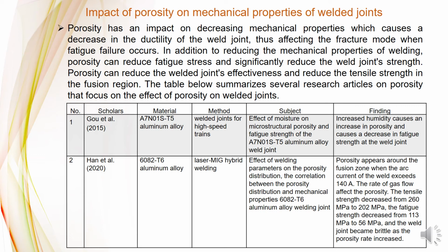Number 2, Han et al. Material: 6082-T6 aluminum alloy. Method: laser-MIG hybrid welding. Subject: effect of welding parameters on the porosity distribution, and the correlation between the porosity distribution and mechanical properties of the 6082-T6 aluminum alloy welded joint. Porosity appears around the fusion zone when the welding current exceeds 140 ampere. The rate of gas flow affects the porosity. The tensile strength decreases from 260 MPa to 202 MPa. The fatigue strength decreases from 113 MPa to 56 MPa, and the welded joint became brittle as the porosity rate increased.